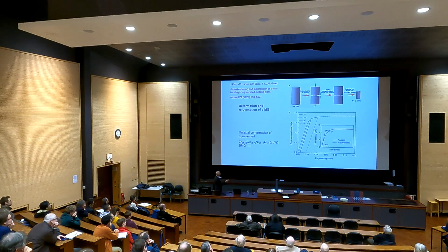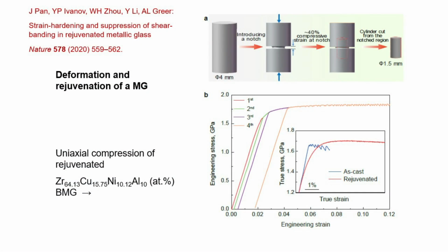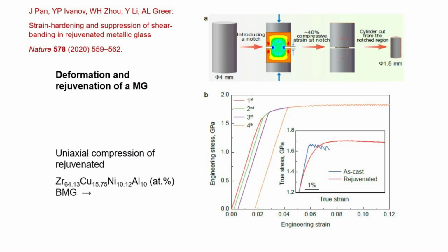But it can be done, and the way you do it is you have a cylinder of bulk metallic glass, you machine a notch in it, you then compress it. The material of the notch is highly deformed under very high stress, but the actual strain is tiny. And amazingly, it becomes less dense, although you're compressing it, and that's this shear dilation phenomenon. If you measure the hardness in a cross-section, it gets about 36% softer as a result of this loading. And there's enough volume, this is 2 millimeters across, so you could actually cut out the entire softened volume, which now becomes our sample for testing.